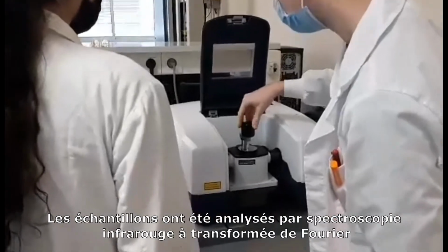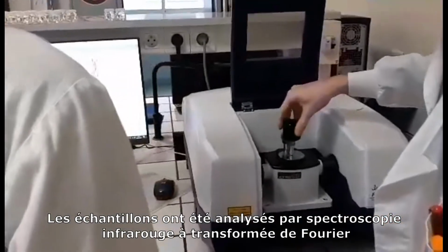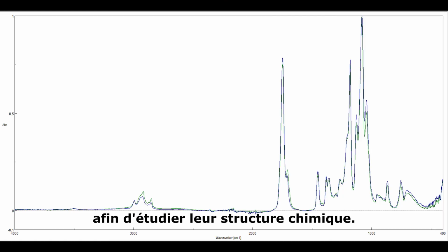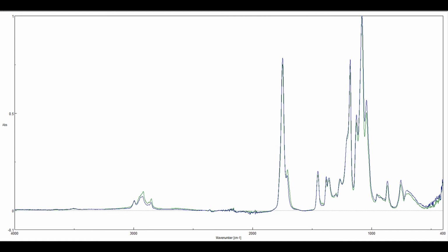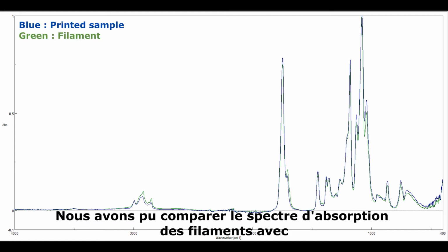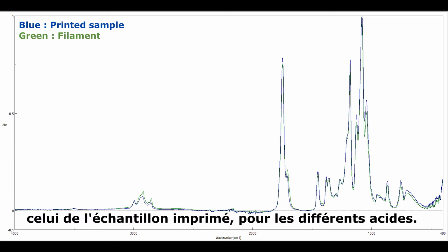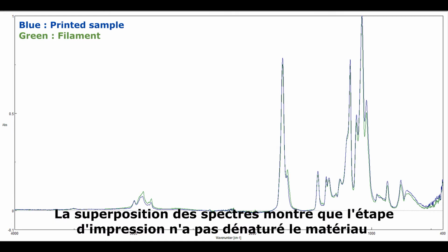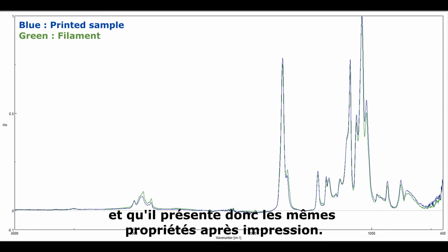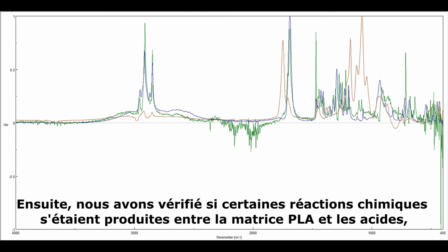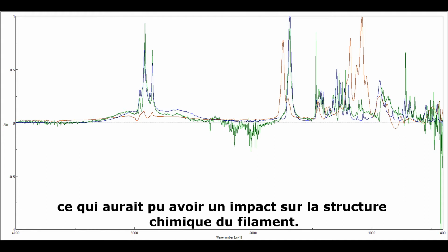The samples were analyzed by Fourier transform infrared spectroscopy in order to study their chemical structure. We could compare the absorption spectrum of the filaments with the one for the printed sample for the different acids. The overlay of the spectra shows that the printing step did not denature the material and thus has the same properties after printing. Then, we verified if some chemical reactions happened between the PLA matrix and the acids, which could have impacted the filament's chemical structure.